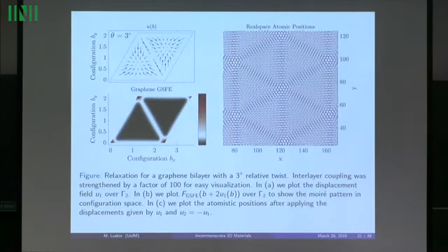Now this shows, again, we've seen this before. It's nice to look at, all the information is really sitting here in the displacement as a function of configuration. We can represent our little U1 function here, and that shows you, again, in configuration space, the generalized stacking fault energy. It shows that we minimize it: most of the region has a very low stacking fault energy, meaning you're at AB or BA.